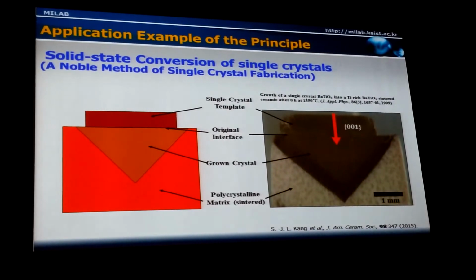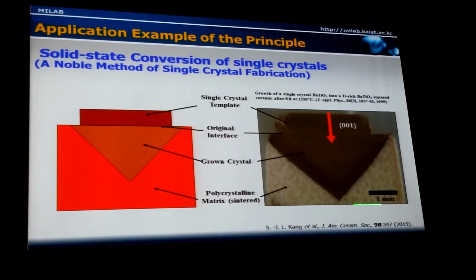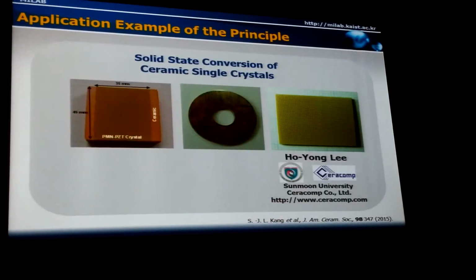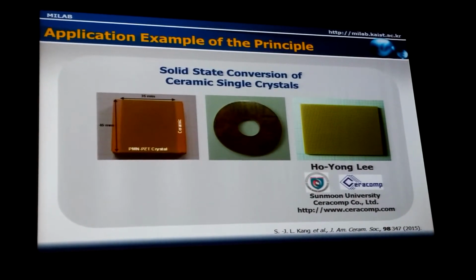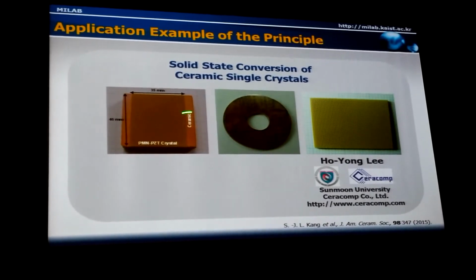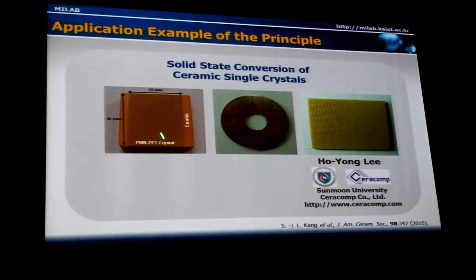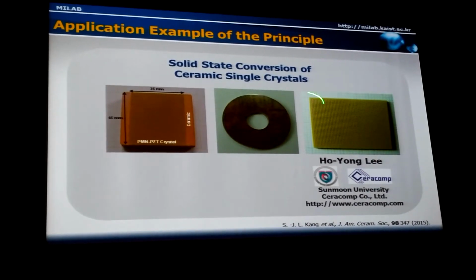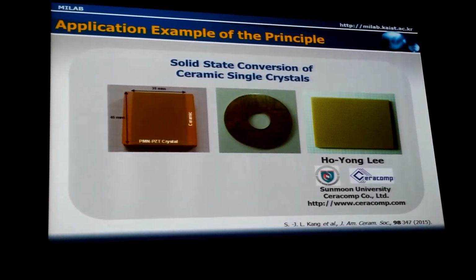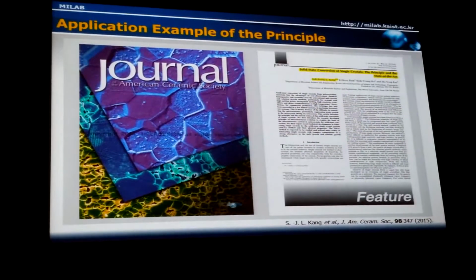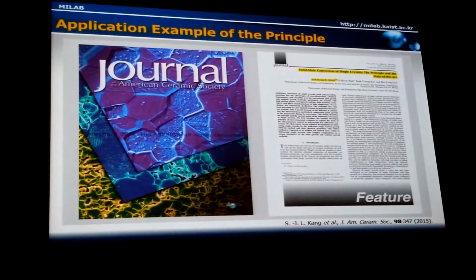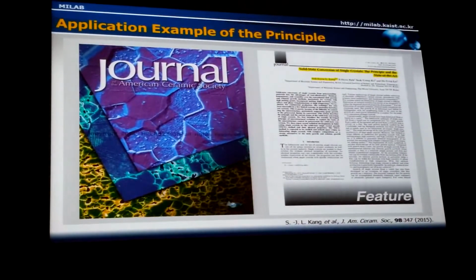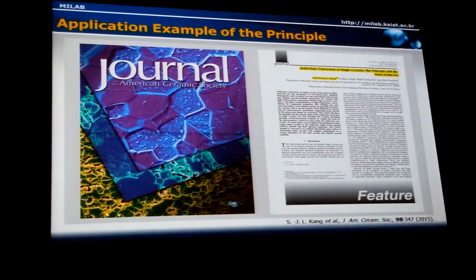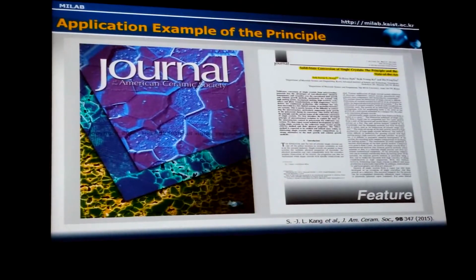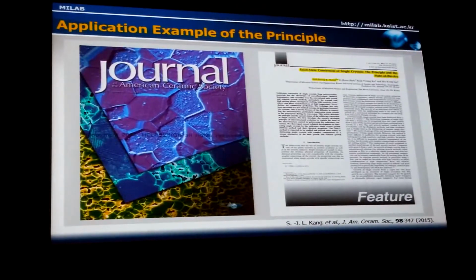And we were able to control the grain growth in the polycrystal in piezoelectric systems. And my colleague, Dr. Ho-Young Lee, Professor Lee, was able to grow big piezoelectric single crystals, as shown here, PMN-PT, centimeter size, and there are ring-shaped, needle-shaped single crystals, also crystal composites. And we wrote together a feature article in the Journal of the American Ceramic Society last February, and we describe all the principles and the application of the principle to grow single crystals, piezoelectric single crystals.